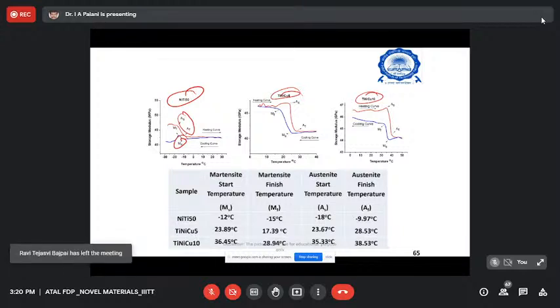So the interesting part in this is, till date, it is very difficult to manufacture a customized structure. Here we could manufacture a customized structure and we could attempt it for an application. But the only challenge involved in this particular case study is the material was getting melted and reheated. Since the material was getting melted and reheated, the property of the material was not to a level as compared to the commercially available system, which was evident from the XRD analysis, where we had a beta phase. Okay, but it doesn't matter.